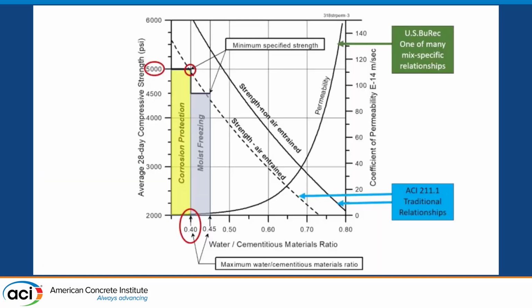If we were to take the ACI 211 default values for the relationships between water-cement ratio and compressive strength, the solid line there is non-air entrained concrete. The dash is air entrained. So we see as the water-cement ratio goes down, the strength is going to go up. And then if we would also take a look at some old Bureau of Reclamation information about how water-cement ratio influences the permeability of the concrete, we would say that if we want a more durable concrete with a lower permeability and other related transport properties, and we want a high strength, then that's going to throw us down to this region of the curve, and this association here where it's going to be moist and freezing,